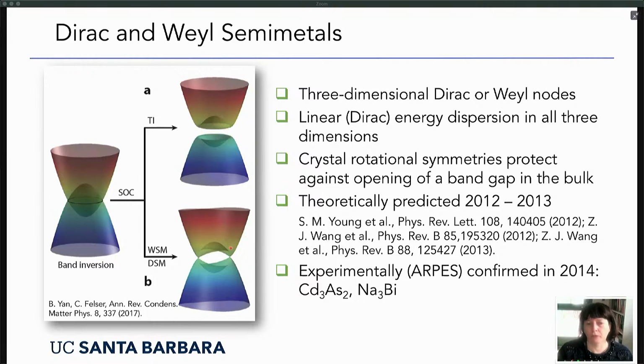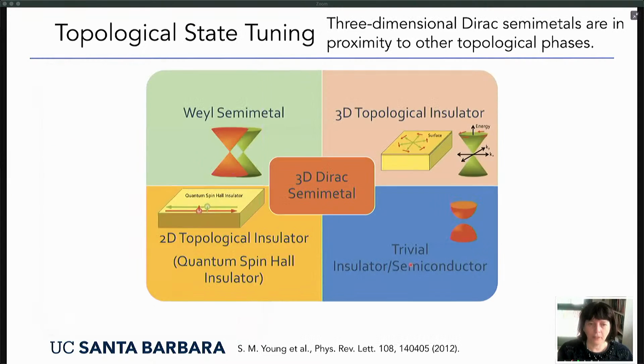We can of course use thin films relatively easily to, for example, break rotational symmetries. So the first materials in this class of materials were predicted theoretically in 2012 and 2013. I've listed some of the key papers here. And then very quickly experimentally, people synthesized these materials and confirmed that they were indeed these three-dimensional Dirac materials using ARPES studies. Right. So there's other interesting properties besides the Dirac nodes and the linear energy dispersion. I'll get back to this.